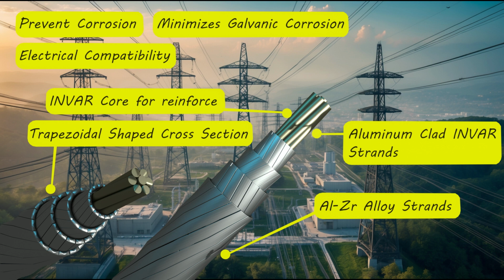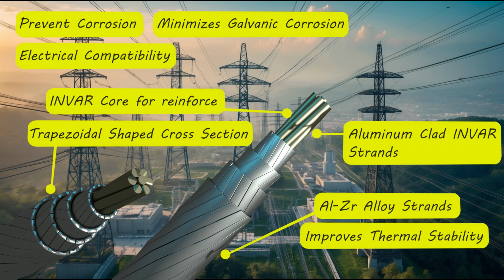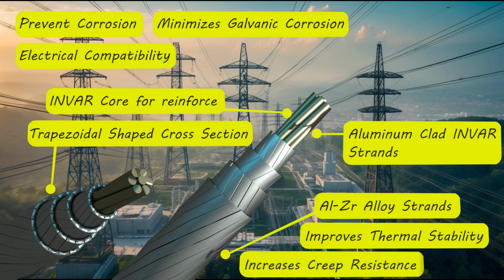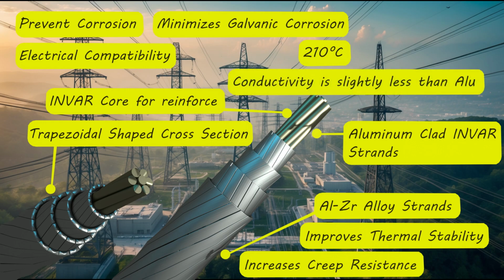In aluminum-zirconium alloy, a small percentage of zirconium is added to aluminum. Adding zirconium to aluminum improves the thermal stability of the aluminum strands. Means, the coefficient of expansion with temperature of aluminum reduces significantly. Adding zirconium increases creep resistance at high temperatures. Aluminum-zirconium alloy allows the conductor to operate at up to 210 degrees Celsius. Aluminum-zirconium alloy maintains good electrical conductivity, although it is slightly less than pure aluminum, but still effective.